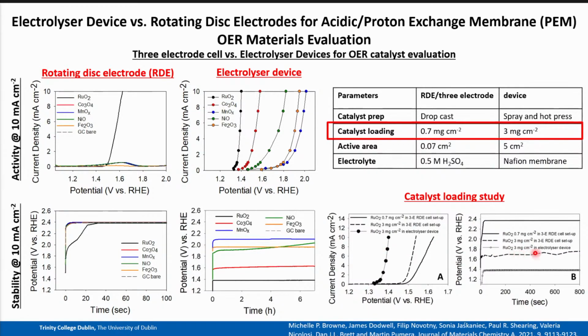In the dashed line, it's the same catalyst loading as the electrolyzer device, but it still doesn't show anywhere near the same activity. So there definitely is a problem, I think, in my opinion, of the rotating disc electrode being the correct platform for OER catalysis evaluation for electrolyzer devices. And so we're not actually the only group, I don't think, that's realized this. There's been a few papers in the last few weeks on this work too. And then also Professor Shannon Boettcher in America has also showed similar results for the OER catalysis evaluation for the rotating ring disc electrode in alkaline media too.